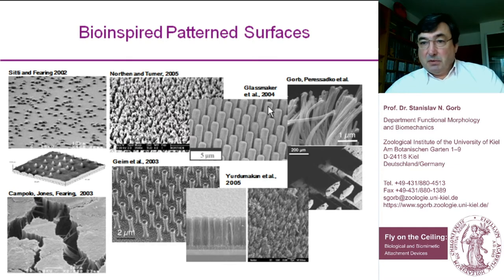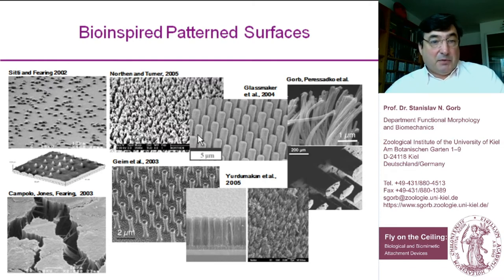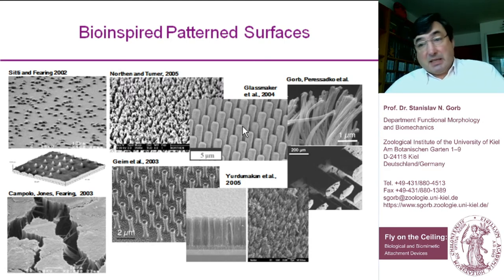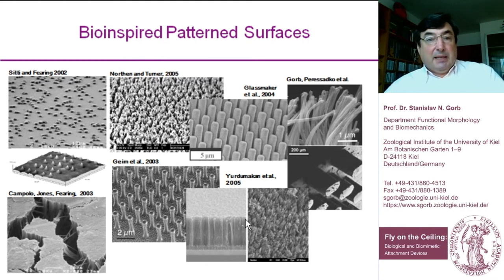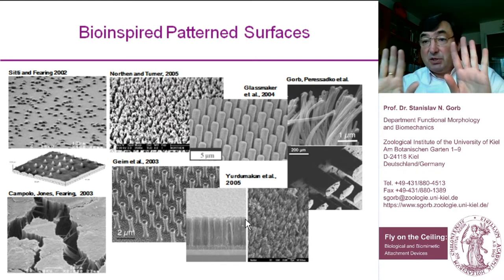Some of the solutions look nice in the SEM, but in some cases the selected material was too stiff, so it did not adhere. Some structures also collapse or condense — you can see this collapsing and condensation. So the problem is: how to solve the challenge of good adhesion while keeping structures apart?